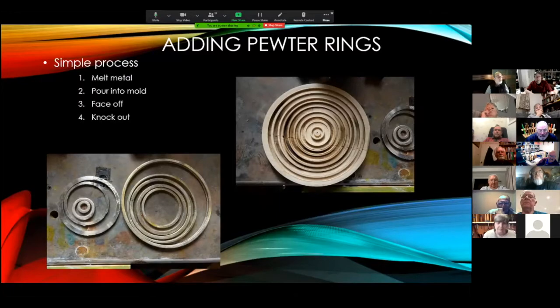And I've now made a jig for making pewter rings. It's a very simple process. Basically, you just melt the pewter, you pour it into the mold, you face off, put it back on the lathe, face it off, and knock the rings out. In practice, there are a few things to watch out for. One is the metal is at 275 degrees or more, so it's very hot. So depending on what wood you're using for your mold, it can actually start to catch fire. So you must wear a vapor-proof mask, because otherwise you're breathing a lot of smoke.